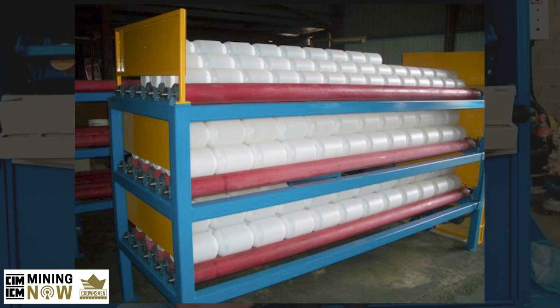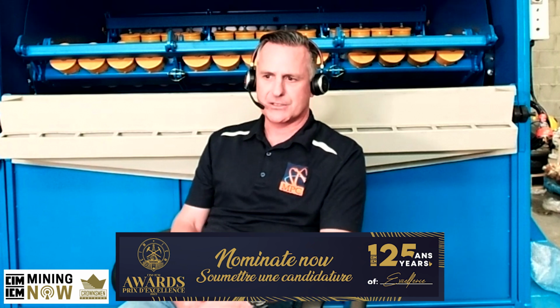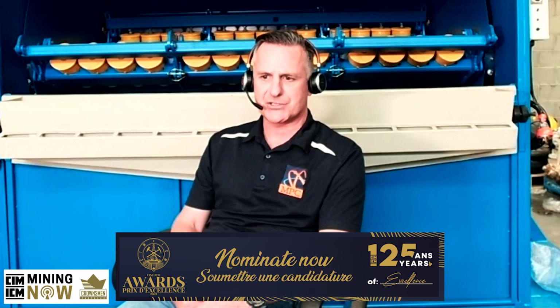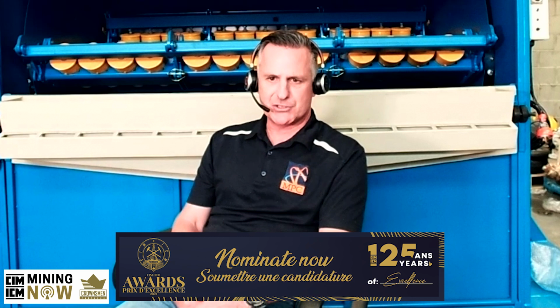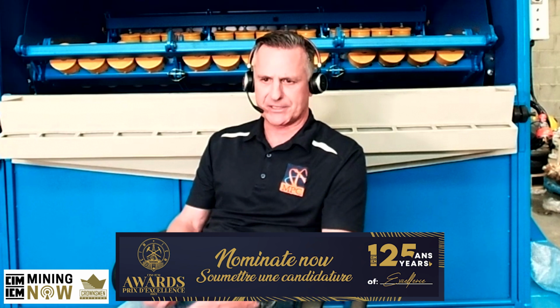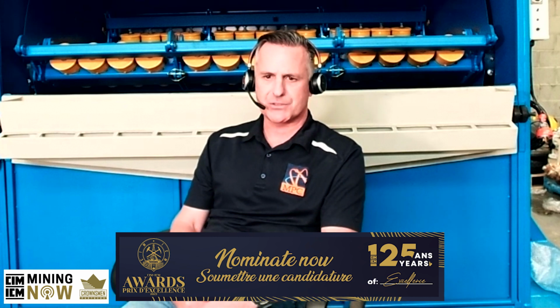And you'll then put it on a roller, which basically agitates that slurry mixture, as you call it, for a period of time: 48 hours, 24 hours, 96 hours. It's a reasonable amount of time depending on the time it takes to get through your circuit, and it will leach the gold out, and it will give you an indication of how much of that gold you can actually recover out of your circuit. It's a standard test, and it's extremely useful for the mill operator to understand the recoverable gold, which is the amount of gold he can get out and then recover via the gold room circuit.